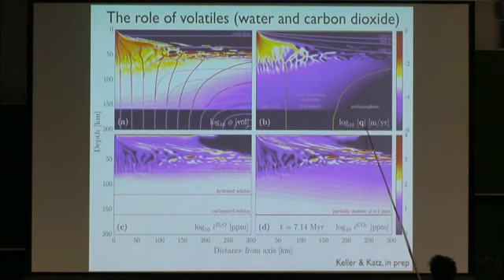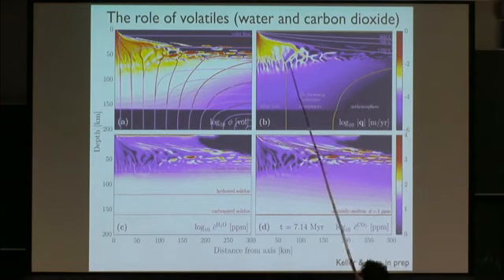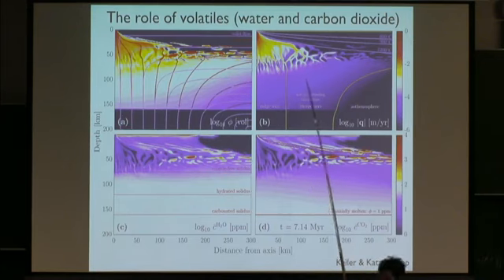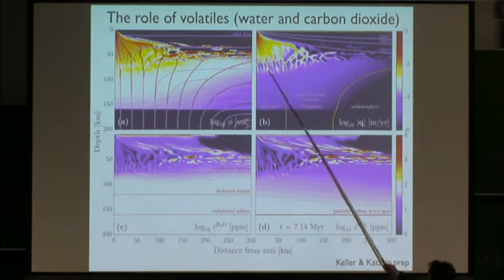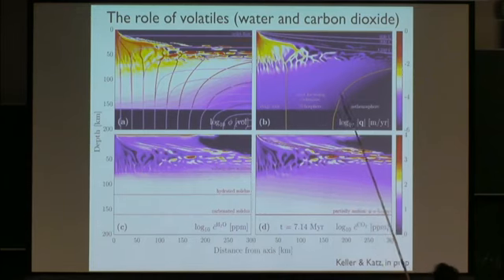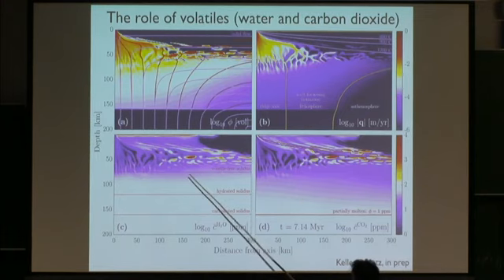This is the log of the liquid flux, so phi w, little w, in meters per year. You really see the channelization here. You can see channels forming at the bottom of the silicate melting regime and penetrating upwards. Right, this is going up to something like 1 meter per year in the flux, and at a porosity of 1%, that translates to about 100 meters per year of the transport speeds. So again, we're seeing rapid transport speeds here with channelization.